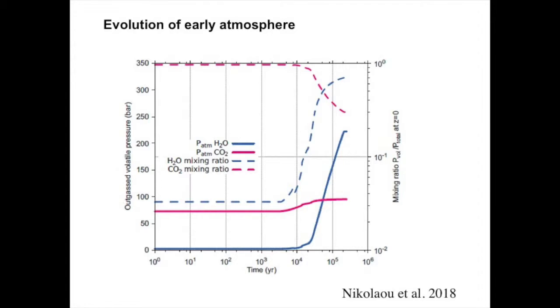So for the evolution of the atmosphere, that's what we see here. That's the outgassing pressure as a function of time for a specific model. But what you nicely see here, take this line, that's the CO2 outgassing, and that is the H2O outgassing. So first CO2 goes into the atmosphere for a long time, because you have a high pressure and the water can't get out.